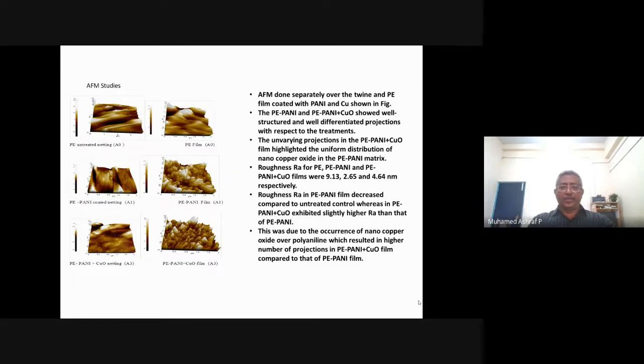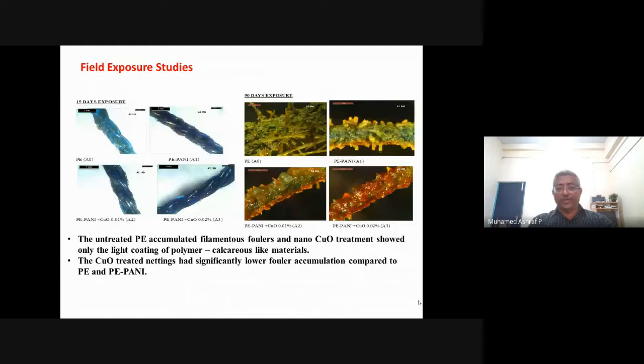And then we analyzed the same through atomic force microscope. You can see that these materials were incorporated in the polyethylene net. And when we exposed it to the field system, you can see 15 days of exposure, and this one after 90 days of exposure in the marine environment. The 0.02% nano copper oxide treated polyethylene nets showed excellent biofouling resistance compared to the control. We can see the control here, and this is the polyethylene treated one, this is one concentration, the second concentration. You can see the clear difference.